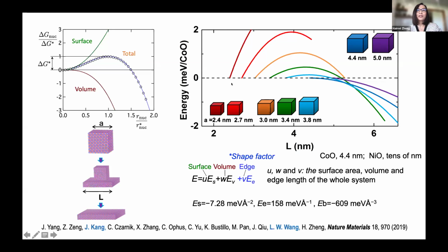When the nanoparticle is small, the energy increases when this 2D type of growth occurs, L representing the spreading part of 2D, and when L increases, this spreading, then energy increases. However, when a particle is large enough, we can see the growth is spontaneous.